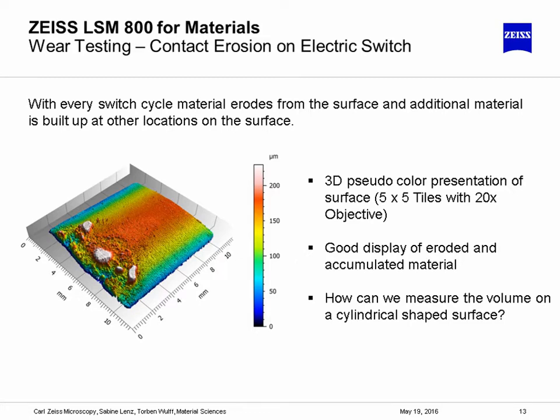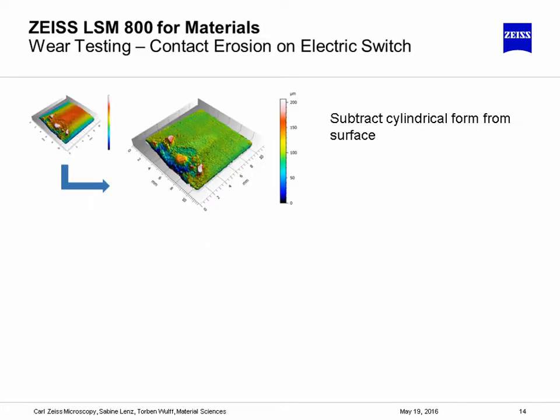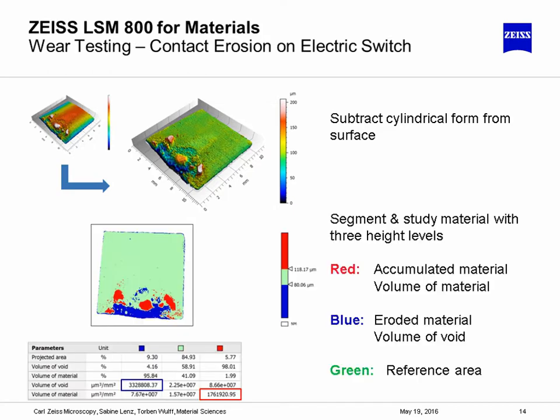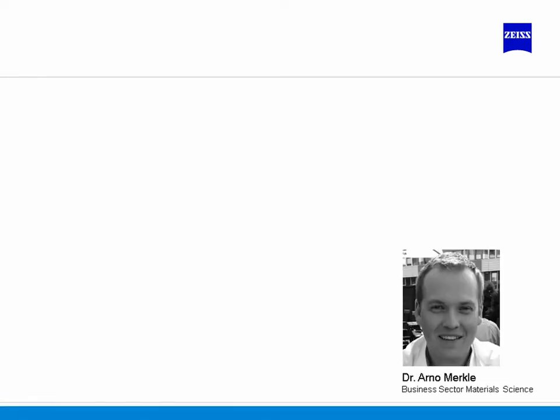As it's run through this 3-dimensional confocal imaging technique, you're then able to effectively obtain that surface roughness and shape information, which then can be measured and quantified. And so you could back out now. You have a cylindrical shape here, but that can then be backed out. You can correct for that volume by subtracting that cylinder from the surface, and then perform various measurements of the void volume or the accumulated material volume, or other quantities here that are depicted in red, blue, and then green here in the lower picture. So that gives you a sense for the 3-dimensional data that can be attained simply using the confocal principle with the new LSM 800 for materials.